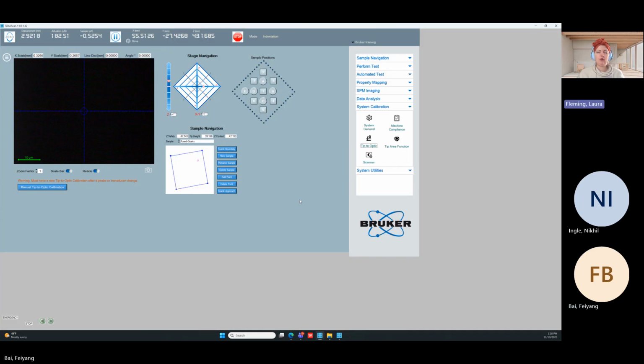Okay. So normally that needs to be done so that when we do an indent into one of our samples, and we ask the system to do the calculation to give us reduced modulus and hardness, we know that those calculations will be correct. If your contact area is correct, your tip area function is correct, then you will get proper results. What kind of results do you think we're going to get from scratch testing? What are we looking for if you look at scratch testing?